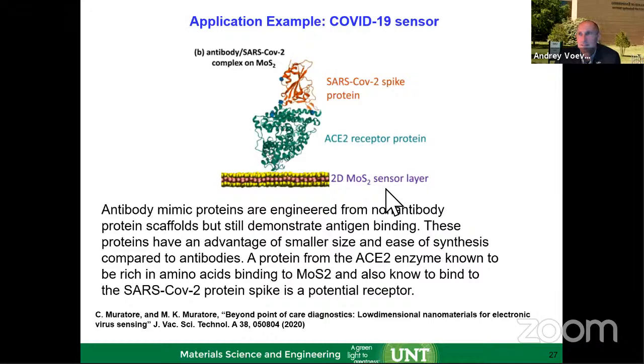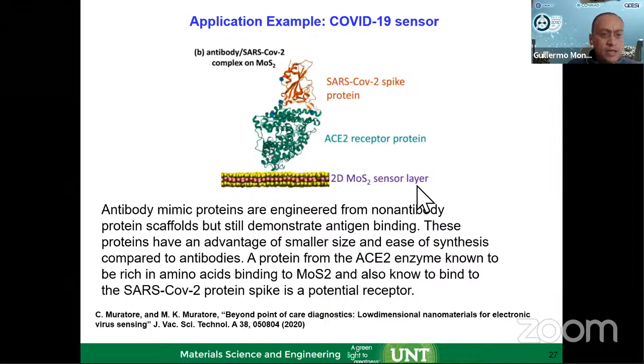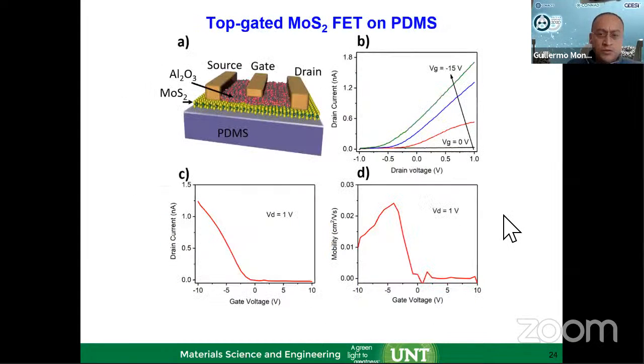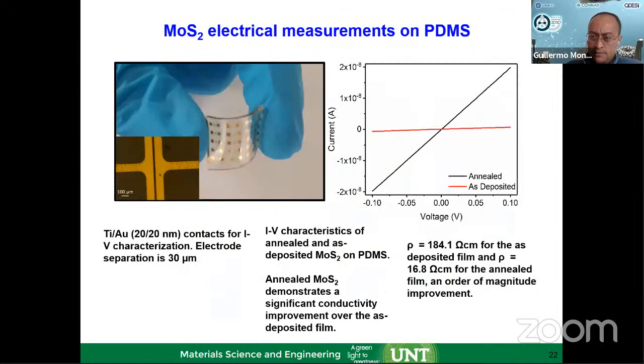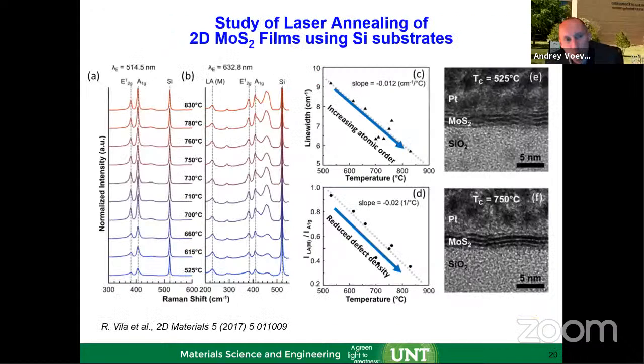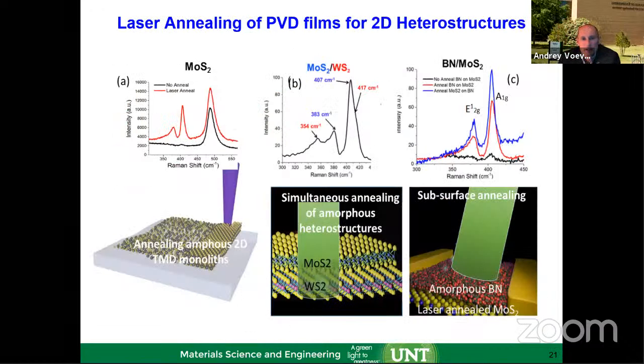Yes, thank you. What are the laser annealing conditions you use for your kind of writing? Are you doing this inside the PVD chamber? Ideally, we would do it within the PVD chamber, but at the moment, we don't have that. So what we grow, molybdenum disulfide, tungsten disulfide, boron nitride, we all grow them in PVD chambers. The annealing is then outside.